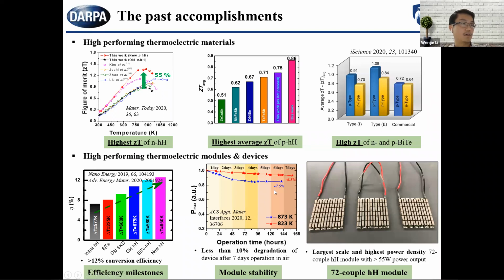On the other hand, the oxidation resistance of the thermoelectric module is another concern for high temperature energy harvesting. Through materials compositional design and brazing techniques, this is one result where we have shown less than 10% degradation of the device after 7 days operated directly in the air, without any inert atmosphere or oxidation resistance coating protection. So this is a very good way to show that the thermoelectric materials and the device itself can have improved oxidation resistance.